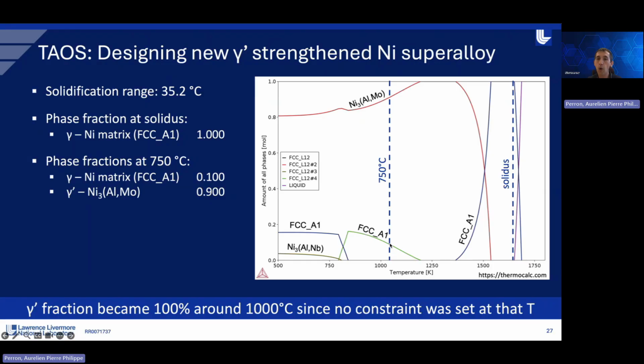However, one thing that we were not happy about during this optimization is that here you can see that at 1000 C or 1250K, all of a sudden you have 100% of the compound. And you want to avoid that because it will crack and become brittle. But that's not an issue of TAOS, right? That's because we did not constrain properly our optimization problem. But that's super easy to fix.